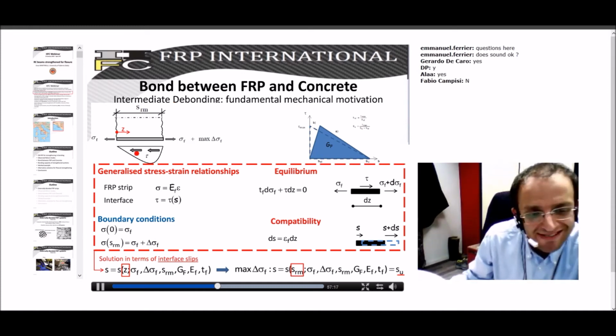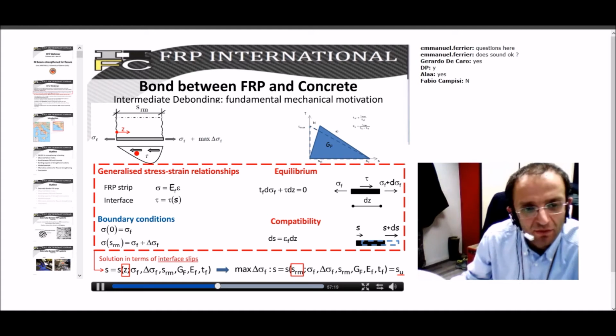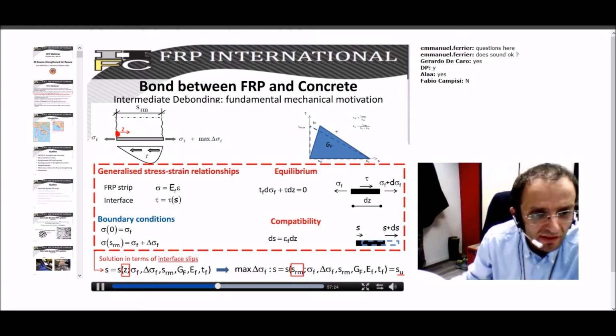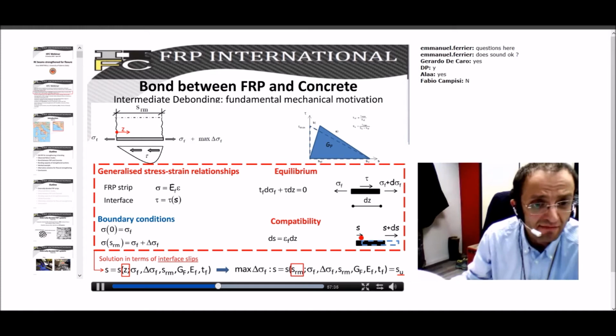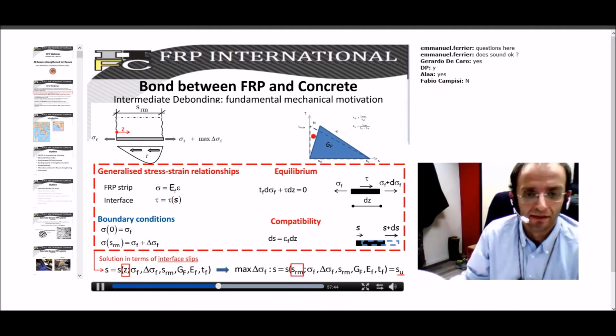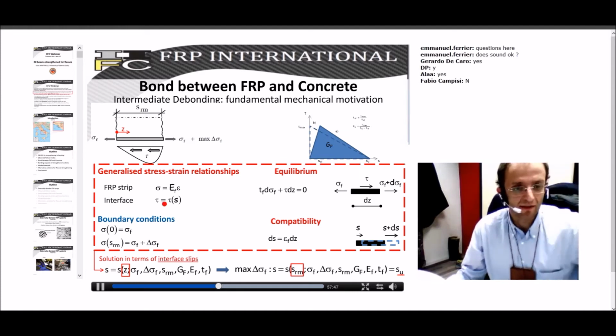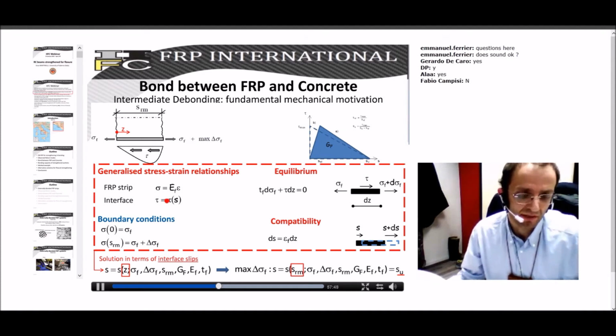The problem is more or less similar to the one we have discussed so far, because we still have a concrete soffit with a concrete substrate with an FRP strip glued on it. We always have this equilibrium equation for a certain segmental element here. The compatibility is the same. The interface is also the same with respect to the plate end situation. We have elastic, non-linear elastic softening behavior for our interface.